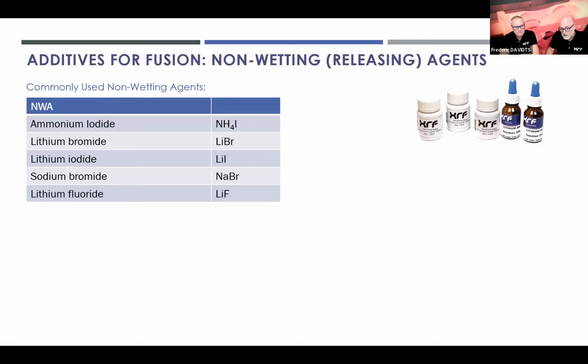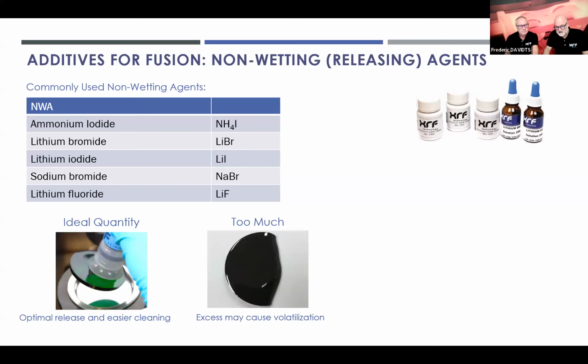And I would say the lithium iodide and the lithium bromide are the most used, but lithium bromide is less volatile and remains more time in the bead. So you have a better effect. If you use lithium iodide, you need to put more lithium iodide in the flux because most of the iodide disappears, and so the effect disappears. If you have long fusion time, iodide is not the best, clearly. And so you need to find the ideal quantity. And of course, if you put too much, you can have a moon effect.